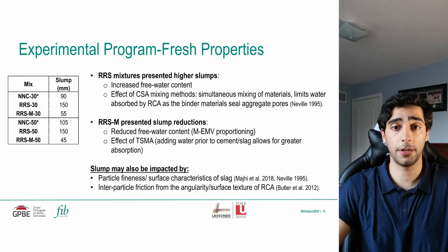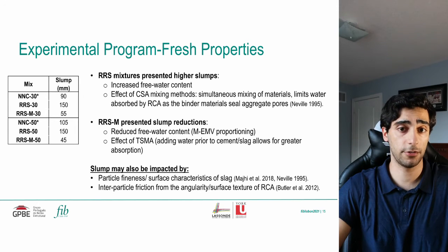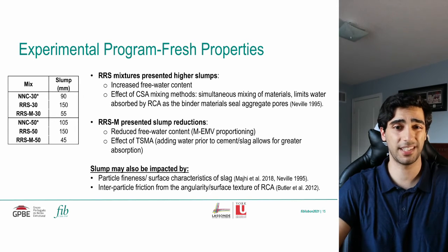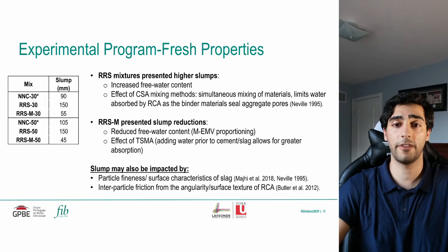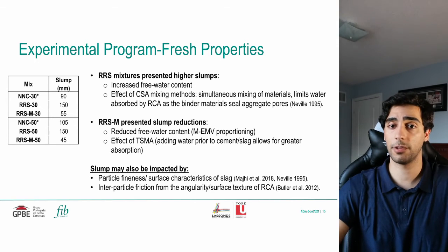In terms of fresh properties, it was found that the RRS mixtures, or the mixtures proportioned with the conventional mix design methods, presented higher slump values, while the mixtures proportioned with the EMV-based method, so the RRS-M mixtures, presented slump reductions. The higher slump values of the first set of mixtures was attributed to the increased free water content, as well as the effect of the CSA mixing methods, consisting of the simultaneous mixing of all materials, resulting in the filling of the pores and lack of water absorption by the aggregates.